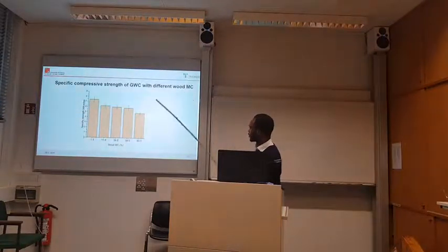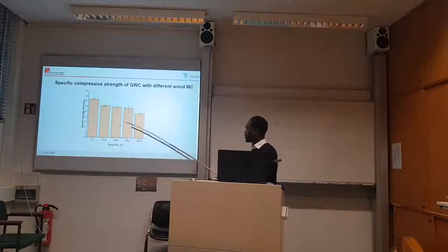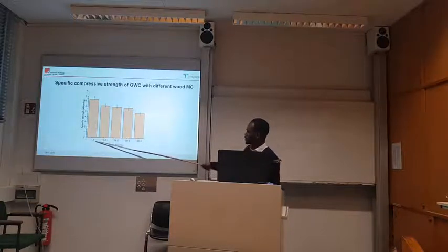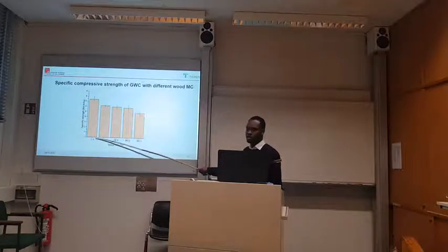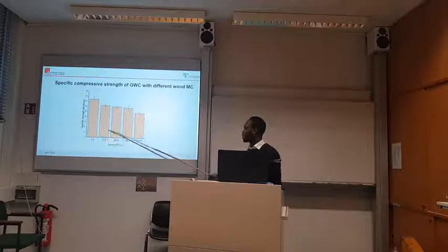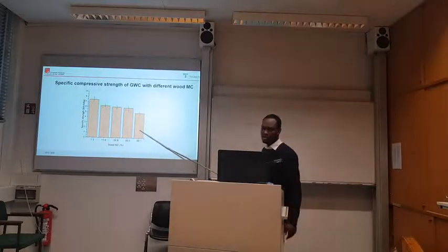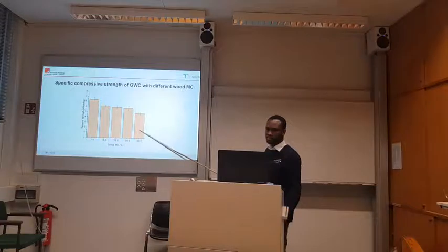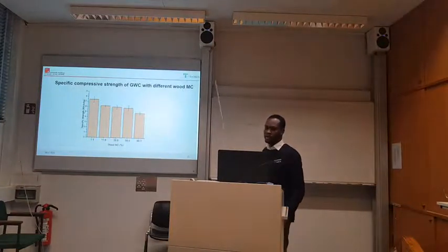And then this is just showing their strength. With the strength, when we have wood that is much drier in the beginning in the mix, the strength is far better than when it's totally wet. Because when it is totally wet, with time the water is coming out.